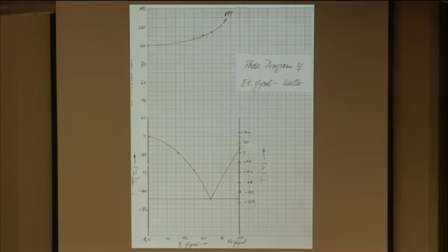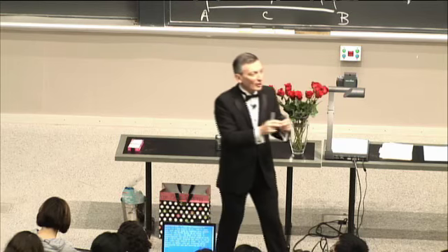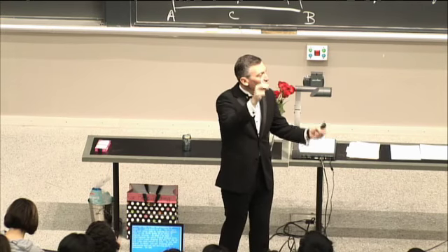Okay. And so what I've done is I've superimposed the solid-liquid diagram with the liquid-vapor diagram, and this is one of the times when nature is kind. So when you add glycol to water, water's on the left here, as you add glycol to water, you get freezing point depression and you get boiling point elevation. So adding glycol to water opens up the liquid range.